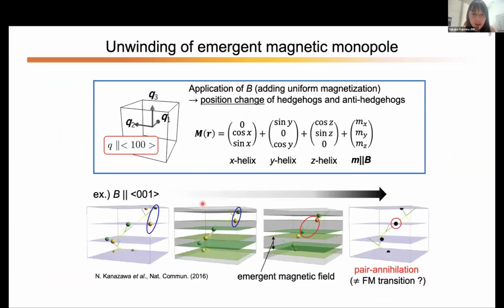spin textures. And then we also explore the unwinding process of the emergent magnetic monopole state under the application of magnetic field. So we assume this as 3 Q vectors, which describes the hedgehog state, and then apply a magnetic field. Magnetic field means adding a uniform magnetization like this. And if we simulate the position of the monopoles and anti-monopoles under magnetic field, we found that there will be a pair annihilation of these spin singularities just before the phase transition.